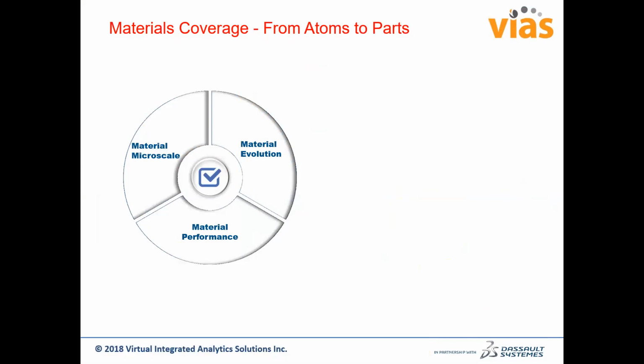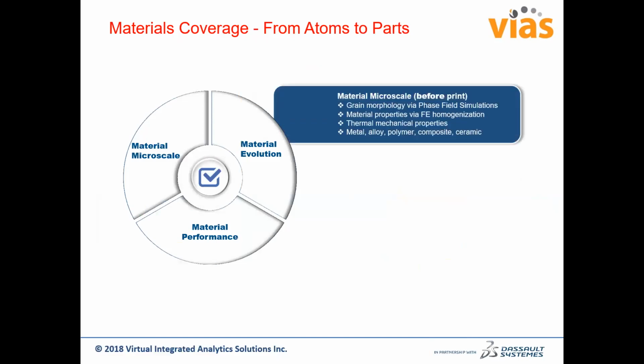One thing to note here is the material coverage. Material here is extremely important. When you work with a steel, you already know the properties of, say, yield and Young's modulus. You put those properties in your FEA and use those numbers for your simulation. Here, the material properties are in effect: your manufacturing process largely changes how your material is going to behave in additive manufacturing. So there is always a need for microscale evaluation to look at the material performance. From the simulation aspect, we can look at the material properties via the finite element homogenization technique, and also there is representative volume element based micromechanics simulation. All this can be brought in to obtain the macroscale properties from the microscale properties.